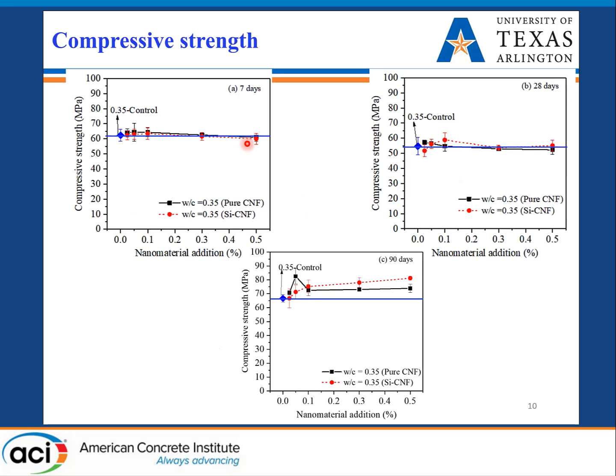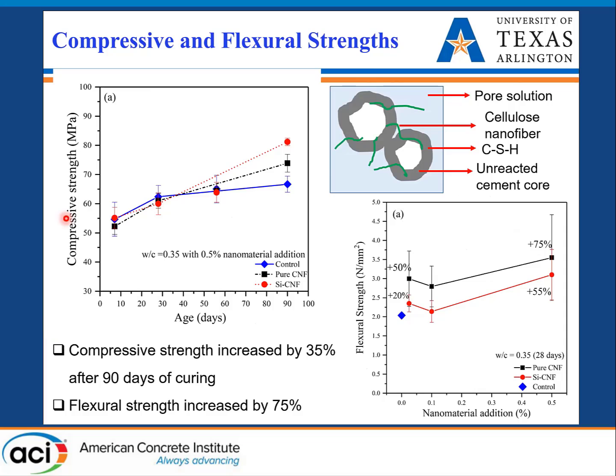Regarding compressive strength: at seven days the blue control line shows no significant variation with cellulose addition. After 28 days there is a slight drop at high cellulose content like 0.5 percent, but not very significant. Interestingly, after 90 days of curing the strength was increasing — specifically the higher cellulose content showed an increasing trend. Cellulose helps diffusion-based hydration reaction and forms higher amounts of reaction product at later stages, which we attribute to the strength increase.